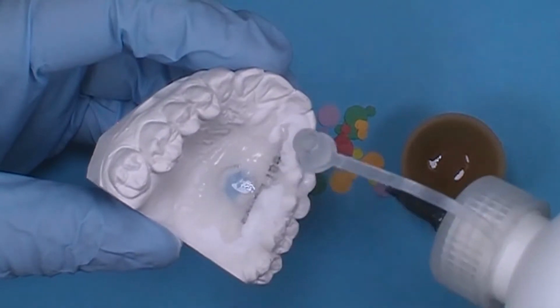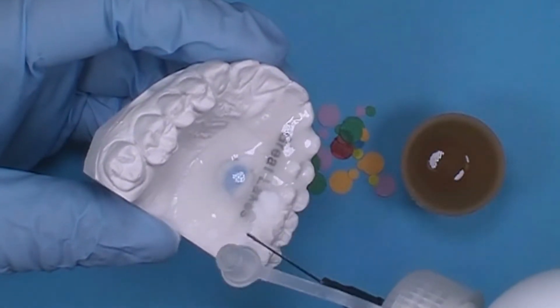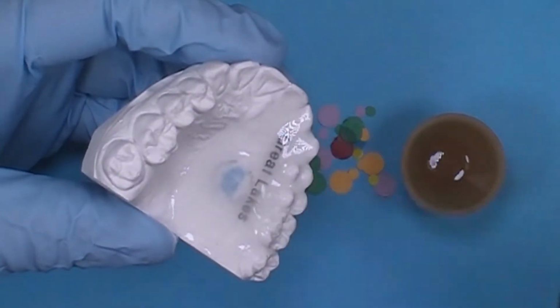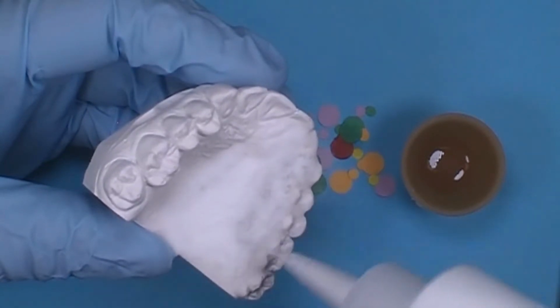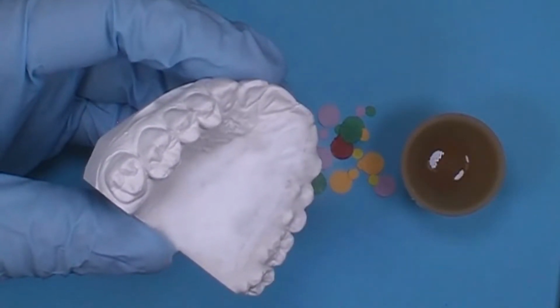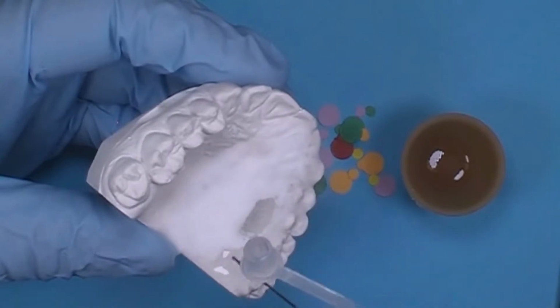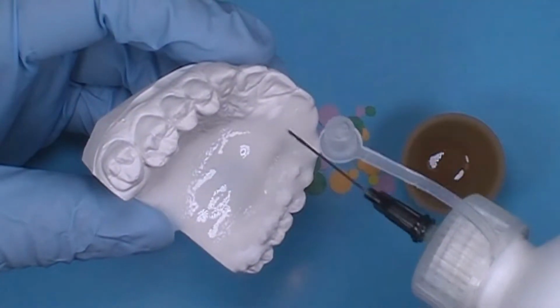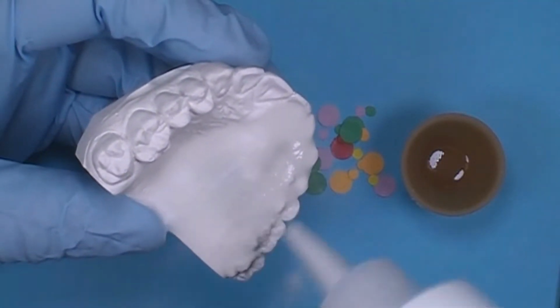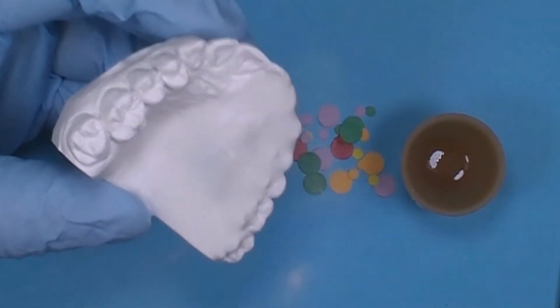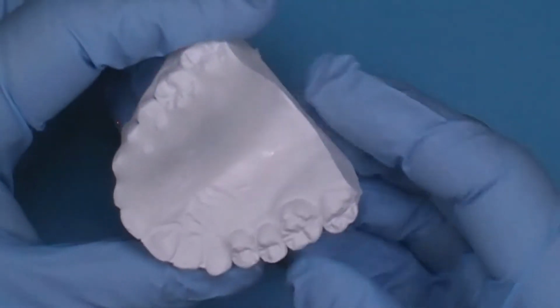If using BioAcryl ice resin, make sure only to use ice polymer with ice monomer. Using other powders or liquids with this material will cause an incomplete acrylic cure. Finish the initial side with a light dusting of polymer to thicken, mix, and prevent slumping. Rotate and tip model to start second half.